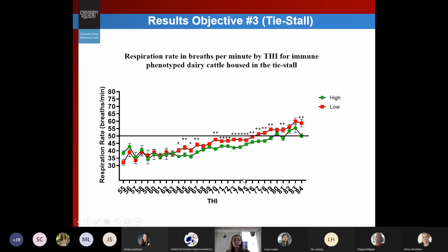This first graph is showing our results for respiration rate. So as you can see from this graph, our high immune responders, which is shown in the green here, had significantly lower respiration rate across a number of different THI values compared to our lows. Additionally, when we get out to that THI of 76, 77, we're seeing our low responders have an increased respiration rate above normal, versus we're not seeing our high responders have an increase in respiration rate above normal until we get out to about a THI of 80.